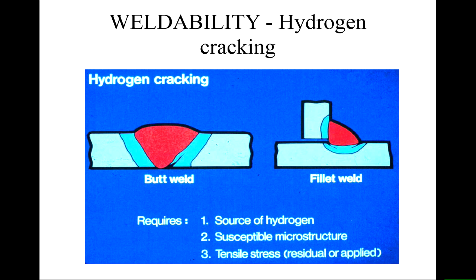Now if you consider this butt weld here, if you clamped either end of the steel and you welded it, you're clamping it so it's all flat, what's happening to the weld metal? It's deposited at a very high temperature, it cools down to room temperature. The steel therefore contracts because its thermal expansion is being driven in the opposite direction. If you clamp the material at either side and you allow it to contract, you're putting the weld metal and the heat affected zone into a state of tensile stress just from the mechanics of welding. So that's the residual stress component, if you like.